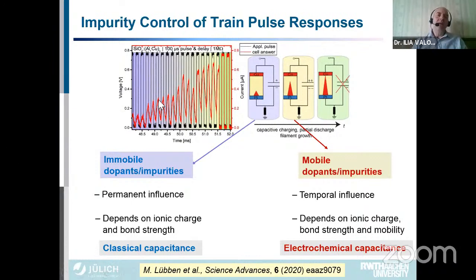Here is a train of pulses applied to the voltage, with 100 microseconds and a magnitude of about 0.8 volt. Initially the first pulses don't change anything. We interpret this as classical capacitance determined solely by the matrix. However, with time, the current starts to increase. I told you that we have accumulation of ions, and accumulation of ions results in changing the electrochemical capacitance, which helps the cell to switch, in fact, to form the filament, until we reach this situation where we have the filament formed in the green area.